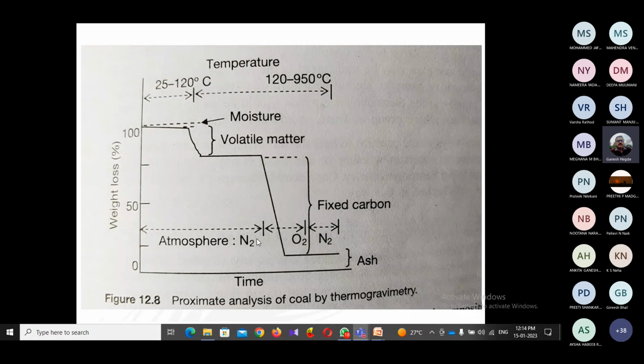And look at this, the furnace atmosphere is changed to oxygen here. Because if you want to study the fuel content of coal, then you have to change the furnace atmosphere to oxygen, because in the nitrogen atmosphere coal cannot burn. If you want to burn the coal you need to have oxygen. Okay, but when you do it in a nitrogen atmosphere, you can study the moisture loss and volatile organic matter. So finally, when you change the furnace atmosphere to oxygen, then the coal will burn, and all the fuel content, the hydrocarbon content in the coal, will combust away, and all of it will be lost as carbon dioxide and water molecules that are driven away.